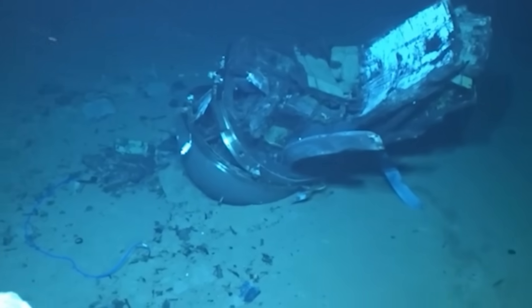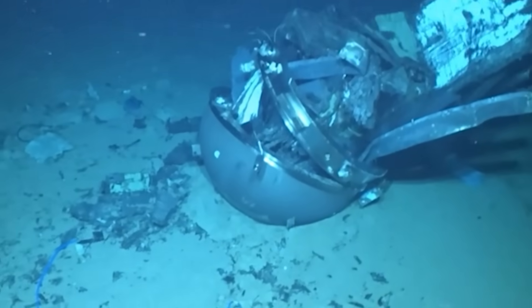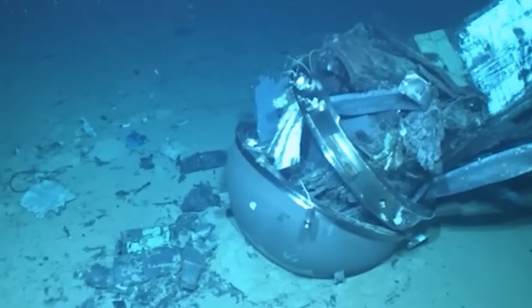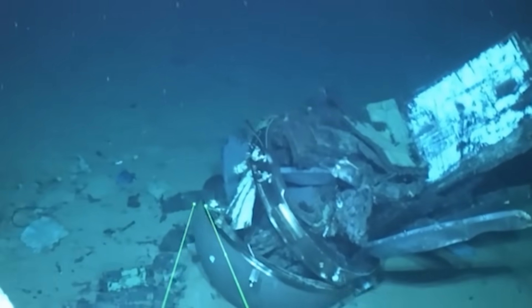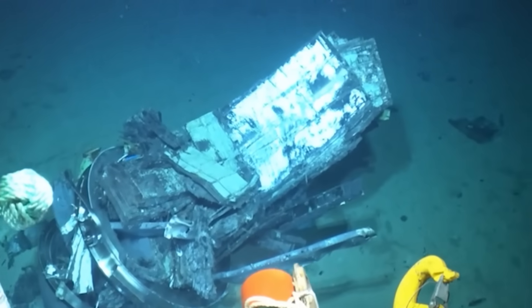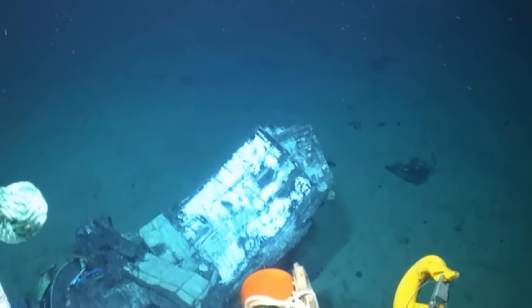Coming back a few yards away to the other section, this does look like the aft titanium dome — you can tell it's still almost intact and didn't come completely separated. The glue sort of held on a little bit there, which isn't surprising because all of the attachments likely cushioned the effects of the implosion. But look at the size of the pieces of black carbon fiber all over the ocean floor. It gives you an idea of how big of a size the implosion reduced the pieces to — it looks like there aren't any bigger than about a foot from the carbon fiber standpoint.